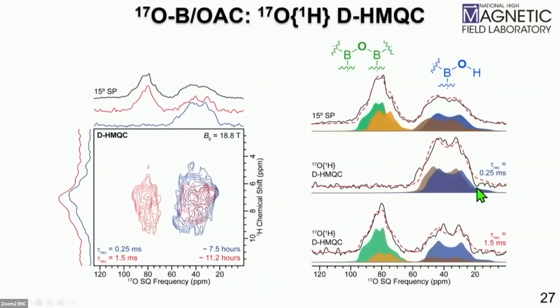hydroxyl groups. Now, what is important is that as we increase our recoupling time and go up quite far, we basically get back out our direct excitation spectrum. And this is important because it is showing that these hydroxyl groups are homogeneously distributed throughout this boron oxide layer, and they are not primarily limited to the surface.